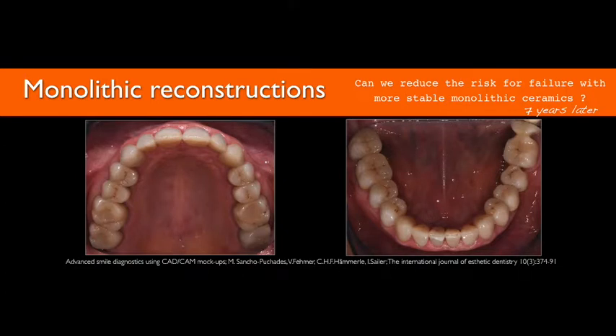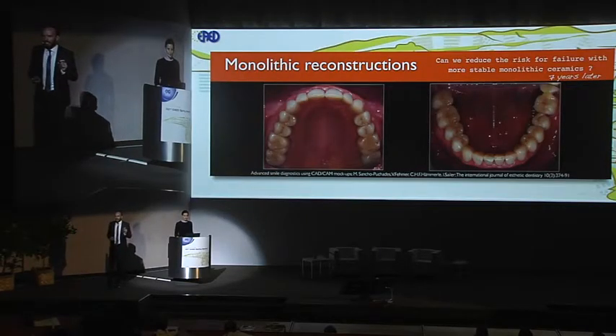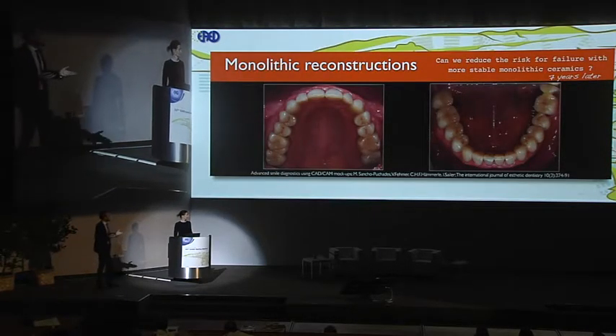and now look at the trepanations that had been done due to the root canal treatments. Even with these thin walls that Irena ended up with, no chippings in the lithium disilicate. So it's close to amazing.